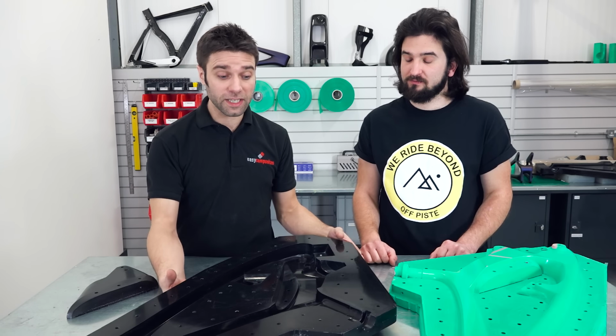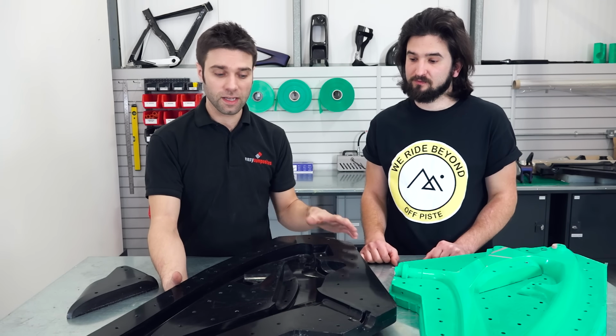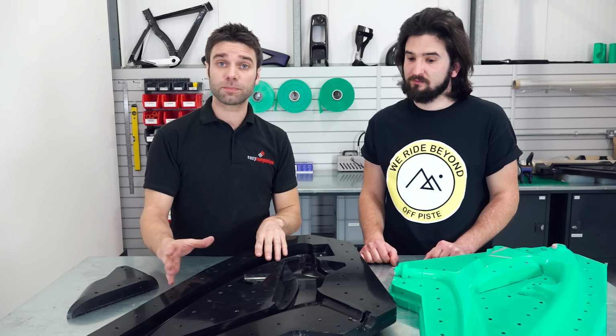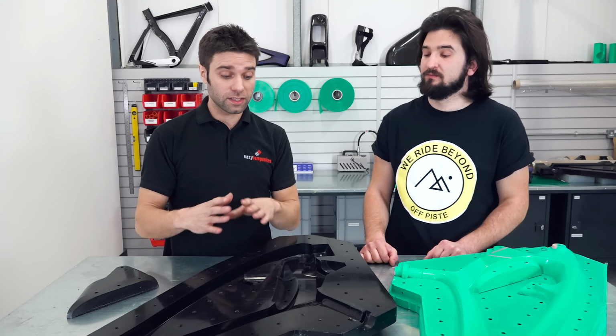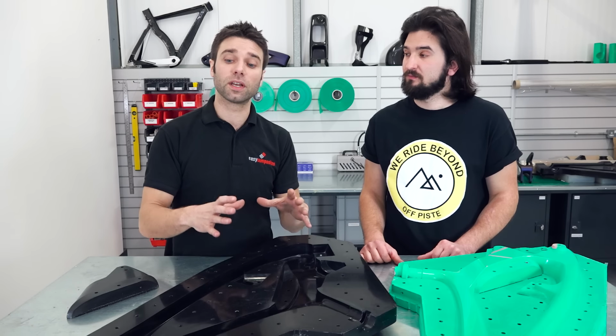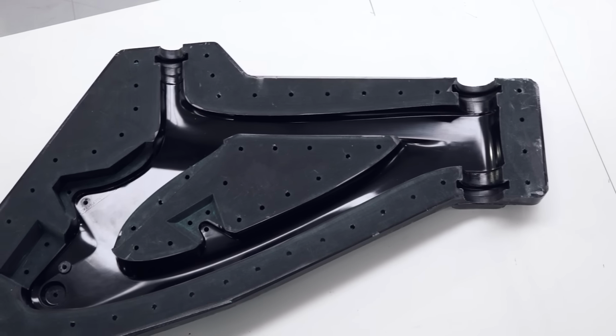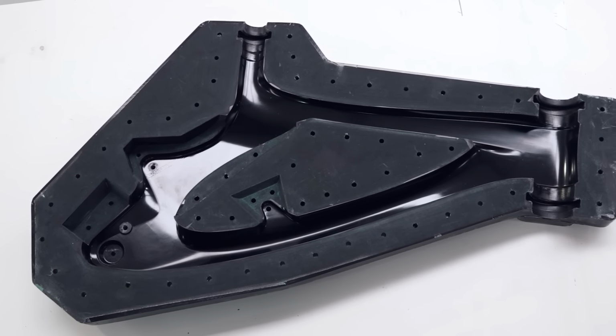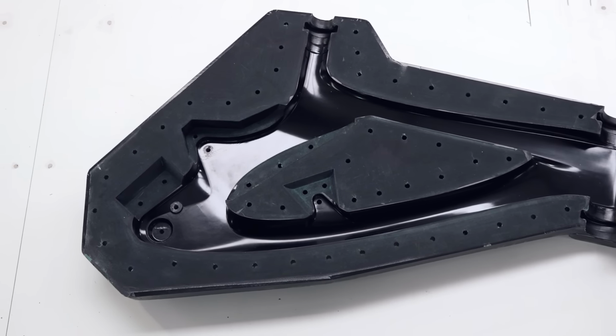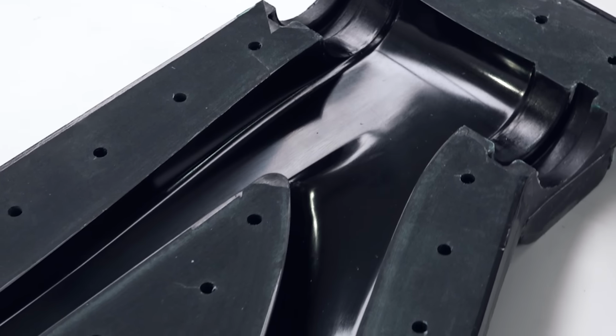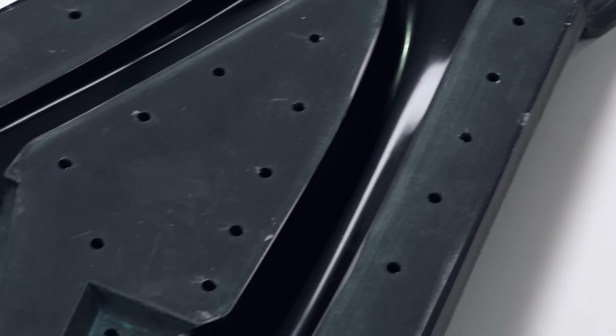Here's the completed mould that's been taken from the pattern. And this has been made from an X-Preg tooling pre-preg. So it's done out of autoclave, so just under vacuum in an oven. And the black surface finish that you see here actually comes from the pre-preg itself. It has a glass fibre scrim cloth that supports pigmented resin, which gives you really excellent tool surfaces.